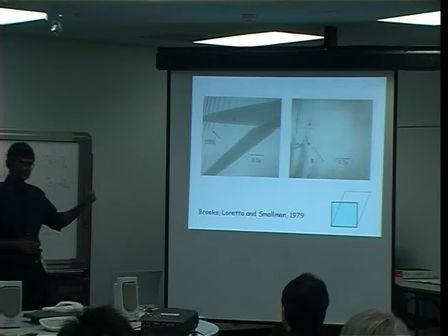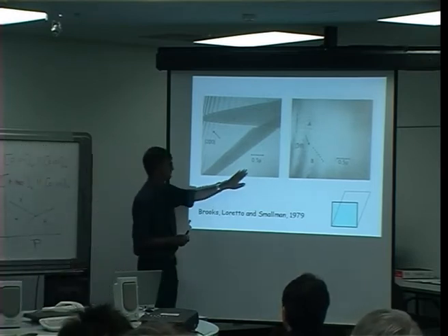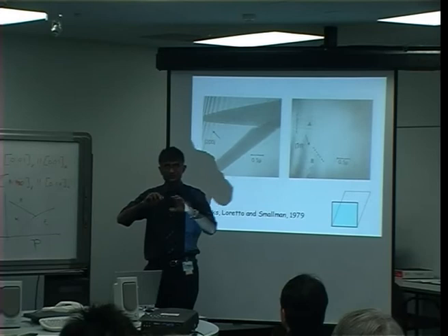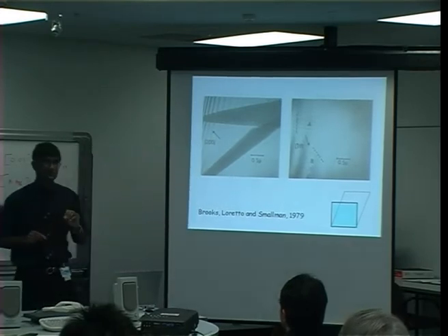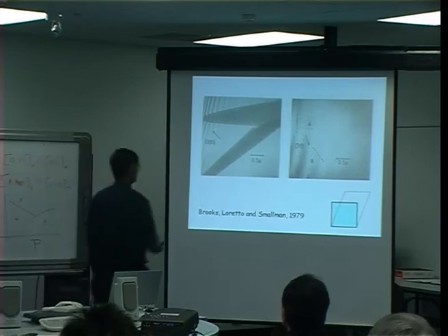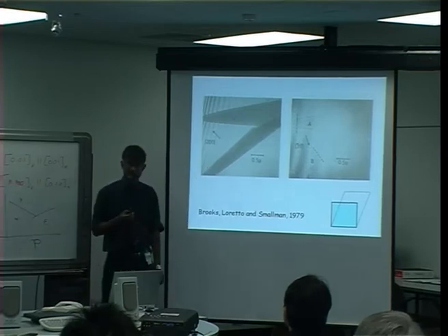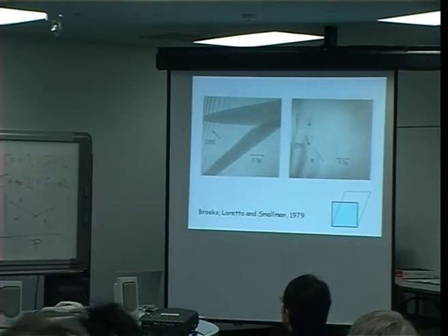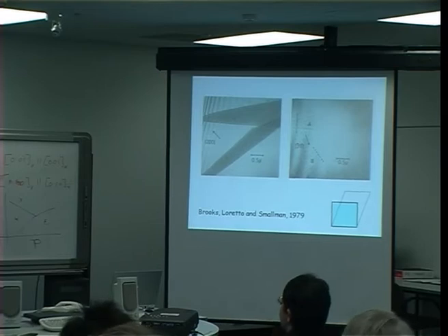This is a transmission electron micrograph of an austenitic stainless steel with a stacking fault. So, you know, instead of the ABC-ABC stacking, there's a mistake, and you have a three-layer deep region with AB-AB stacking. So you could imagine that this is actually epsilon martensite. Okay? But, you know, this sphere model that we use of atoms isn't quite correct, because the volume of the hexagonal close-packed iron is less than that of the austenite. HCP iron is actually denser than austenite. And you can't predict that from a hard sphere model.